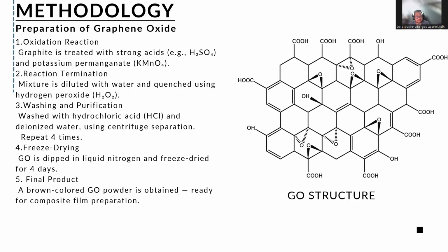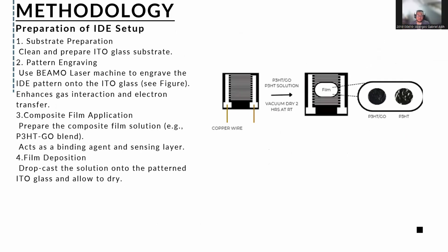So the preparation of GO. For the oxidation reaction, graphite is treated with strong acids. Then reaction termination: the mixture is diluted with water and quenched using hydrogen peroxide. For the washing and purification, it will be washed by hydrochloric acid and deionized water using centrifuge separation, and it will be repeated 4 times per liquid. Then for the drying, GO is dipped in liquid nitrogen and freeze dried for 4 days. The final product will be a brown color GO powder, and it is ready for composite film preparation.